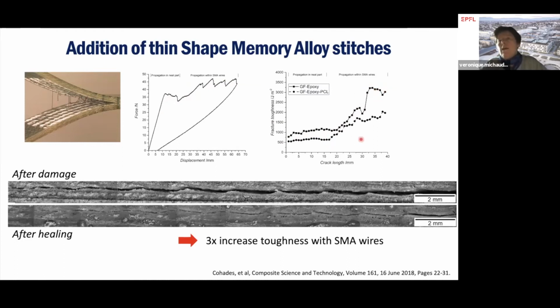This has been well known, actually. Adding stitching increases a lot, and we elucidated the various mechanisms that take place. However, we see also that after damage, we have the crack that is open, but after healing, the fact that we heat up will help also the shape memory alloy wires to shrink and to close the crack. So this really improves the crack closure and the healing.